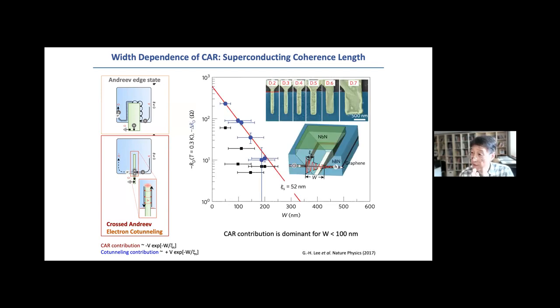Indeed, if we just vary this superconducting contact width from, say, below 100 nanometers to a few hundred nanometers, you can see that the negative signal we are getting exponentially decays with this width of the superconductor. The parameter we can extract out of this is basically the superconductor coherence length, which is about a 50 nanometer-ish length scale, which more or less agrees with what we expect to see in niobium nitride, the superconductor. So at least we know that the basic idea of using these cross-Andreev reflections to probe the proximitized quantum